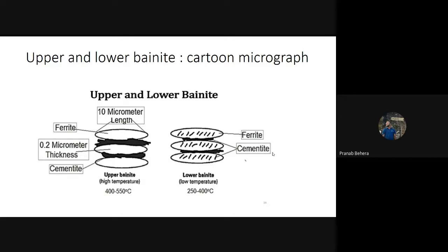And if you remember, bainite is formed by continuous cooling or isothermal cooling of steel from austenitizing temperature? Continuous cooling. Isothermal cooling, but directly isothermal cooling, or you have to do something initially? Continuous cooling, then there is a holding time. Very good, very good. You have to do fast quenching, a very fast rate of cooling from austenitizing temperature to bainitic transformation temperature. And after reaching bainitic transformation temperature, you have to hold the sample for a long interval of time. So first is quenching, and the second stage is your isothermal cooling, right?